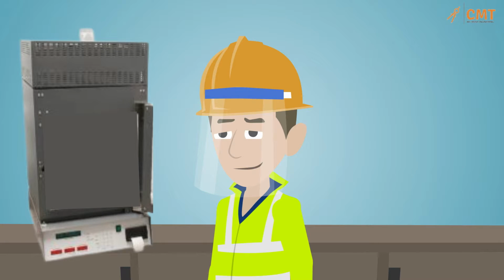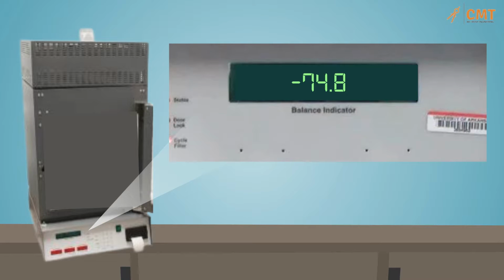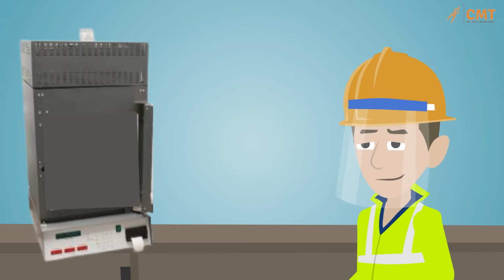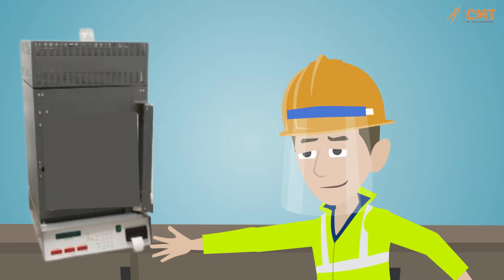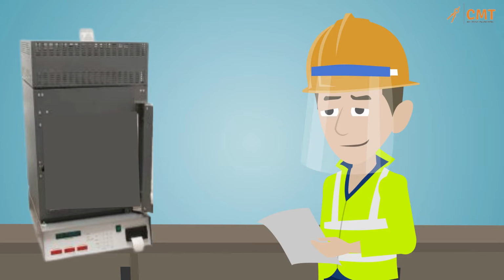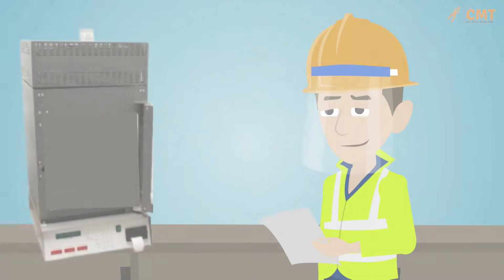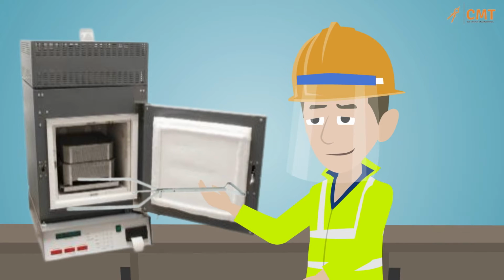The mass loss may be monitored on the oven display. When the ignition oven detects no additional loss over a 3-minute time period, the burn is complete. You will stop the burn sequence and collect the data ticket. Then record the calibrated asphalt content from the ticket to the nearest 0.01%. Next, you need to remove the basket assembly from the ignition furnace with the loading fork.